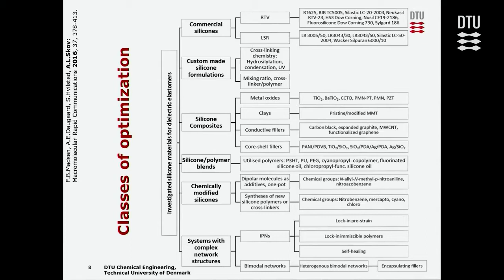And then also, I think one of the most important issues we raised in the review was to tell people a bit about the mixing ratio, the cross-linker polymer ratio. To get really nice actuation is actually by cheating and not adding enough cross-linker. Then we get back into the problems we see with the VHB tapes.